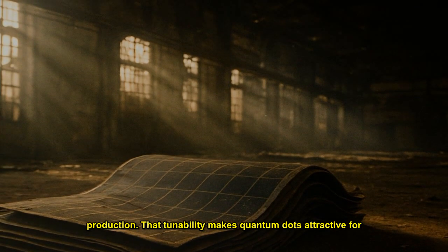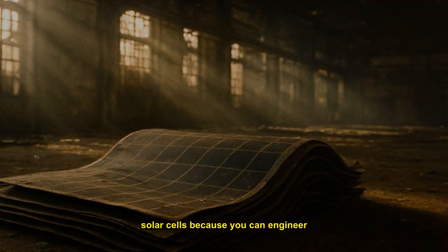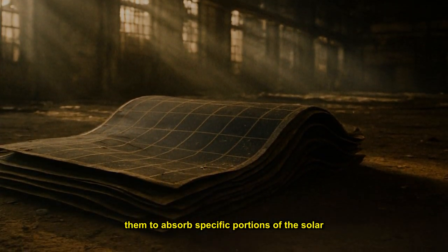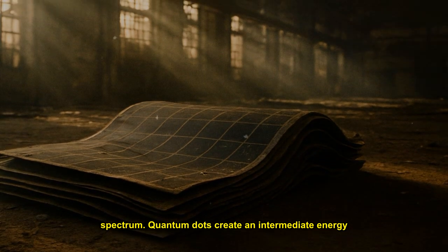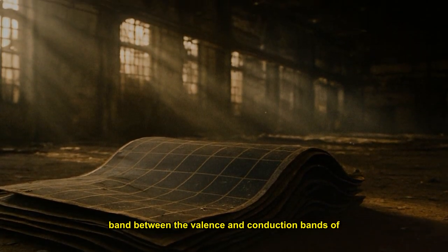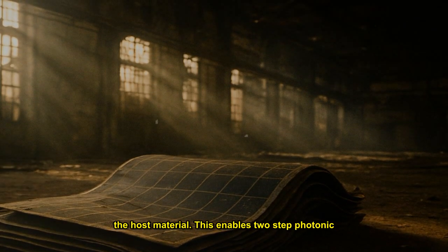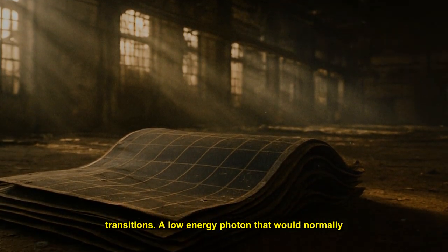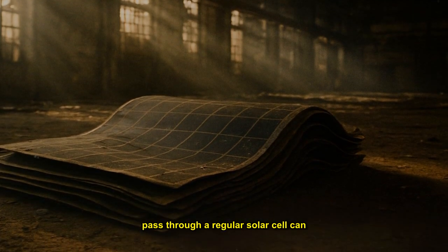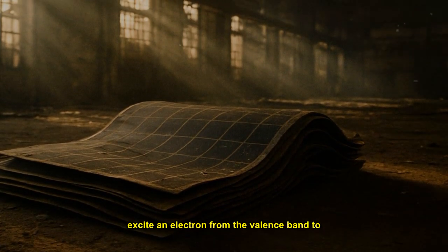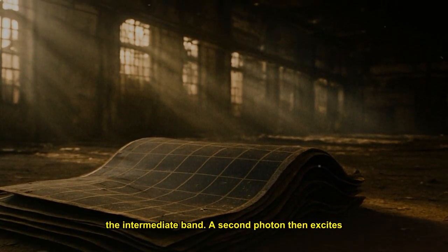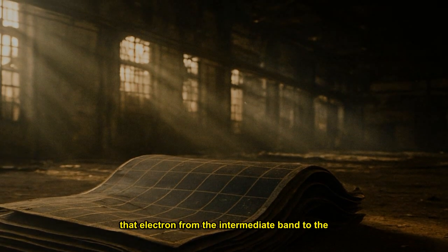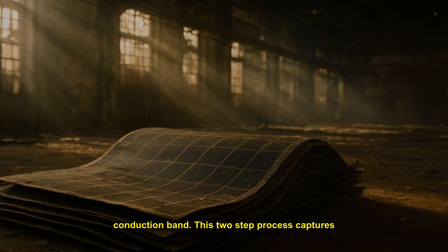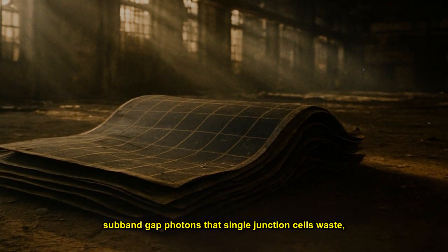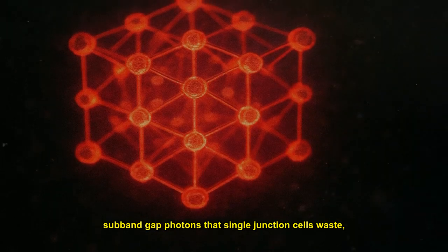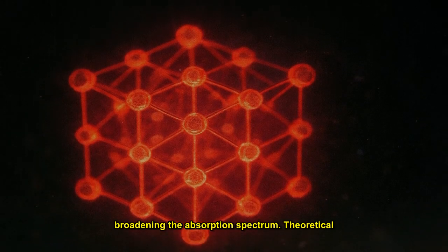That tunability makes quantum dots attractive for solar cells because you can engineer them to absorb specific portions of the solar spectrum. Quantum dots create an intermediate energy band between the valence and conduction bands of the host material. This enables two-step photonic transitions. A low-energy photon that would normally pass through a regular solar cell can excite an electron from the valence band to the intermediate band. A second photon then excites that electron from the intermediate band to the conduction band. This two-step process captures sub-band gap photons that single-junction cells waste, broadening the absorption spectrum.